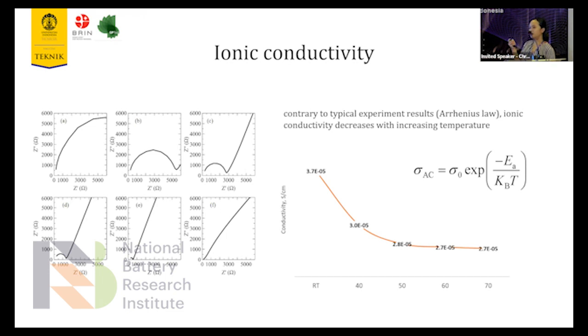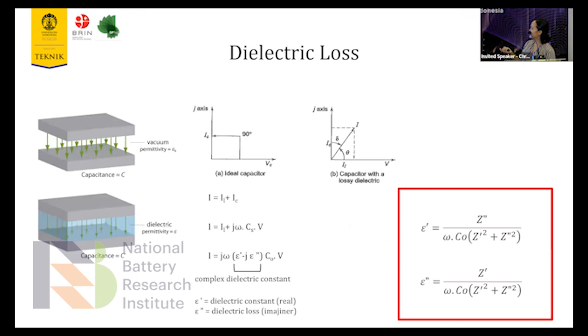So we are looking for the answer by first analyzing the dielectric loss. We see that for ideal capacitor, we have 90-degree angle as we move the voltage. We have the current, but with a lossy dielectric, we have tan delta, which can be defined as the dielectric loss. So at the formula here, the epsilon prime and epsilon double prime, we translate the impedance we get from the measurement into the dielectric constant and dielectric loss.